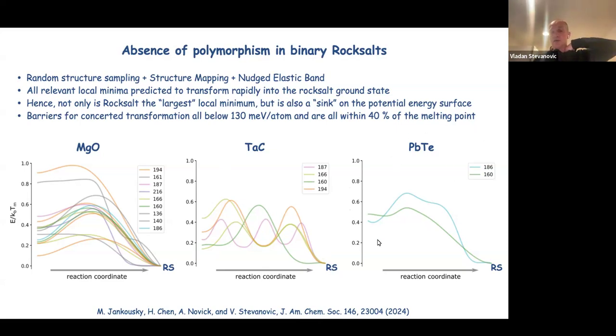And then for lead telluride, we literally find only 2 local minima in addition to rock salt that are more statistically relevant, and the result is pretty much the same. So this again adds to our discussion of magnesium oxide from the beginning, and pretty much explains why we don't see polymorphism or metastable structures in binary rock salts, by extension, of course, from these